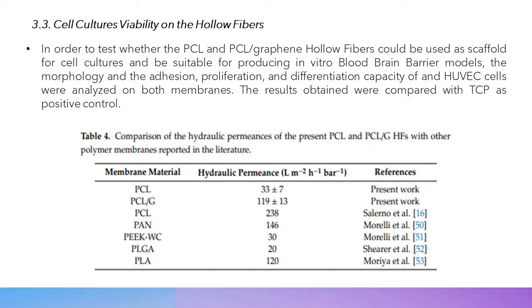In order to test whether the PCL or PCL graphene hollow fibers could be used as a scaffold for cell cultures and be suitable for producing in vitro blood-brain barrier models, the morphology and the adhesion, proliferation, and differentiation capacity of the HUVEC cells were analyzed on both membranes. The results were compared to the TCP as positive control, as you can observe here in Table 4. Overall, water permeance results were consistent with the ESEM imaging, which showed the high porosity values of the hollow fibers.